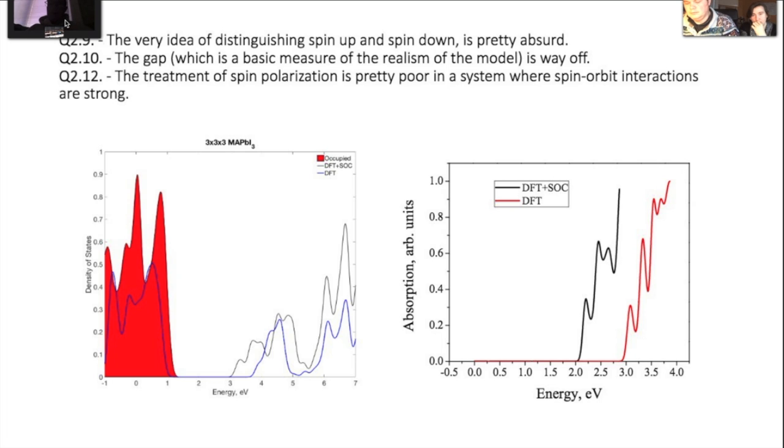And so also showing the absorption for these values with and without the spin-orbit coupling, you can see that the initial onset is jumping from about 3 to somewhere around 2 eV. So we're getting closer to the actual value. And I think if we would shift over one more, to either include multiple K points with spin-orbit coupling, or just take a single point spin-orbit coupling at the R point, you would see that band gap reduce even further, matching that of the experimental.